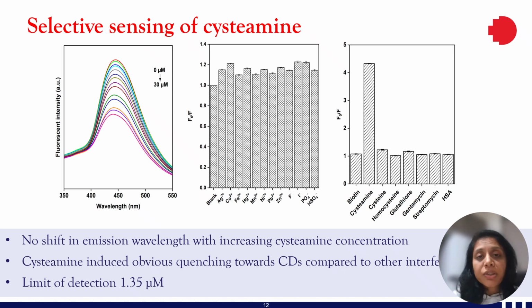Further, to validate the selectivity and specificity of glutamic acid and tryptophan carbon dots for the detection of cysteamine, an interference study was conducted. Here we have used different interfering cations and intracellular thiol molecules. As we can see here, only cysteamine could induce obvious quenching towards glutamic acid and tryptophan carbon dots when compared to other interfering substances. So these results demonstrated that the glutamic acid and tryptophan carbon dots exhibit very high selectivity towards cysteamine.